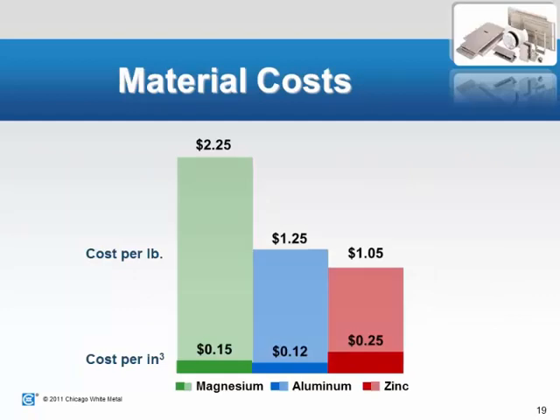This slide shows the material costs, and again, this is a snapshot of, I don't know, a couple weeks ago, relatively up to date. But again, this fluctuates during the year. We show the larger bar is the actual cost per pound of the alloy itself. So for magnesium, right now the cost is about $2.25 per pound. Aluminum is about $1.25 in that area, and zinc is about $1.05. So that means something, but it doesn't mean as much as when you factor in the cost per cubic inch, or the cost per unit volume. So that's why we show a second bar in here that shows, when you factor in the density and actual weight of the alloy, how that comes out.